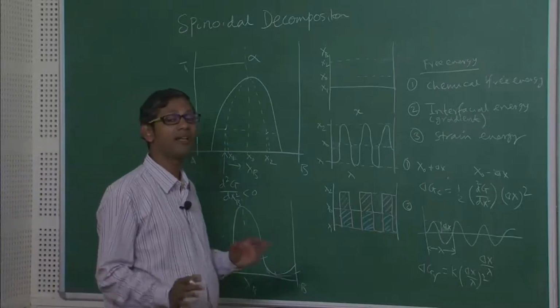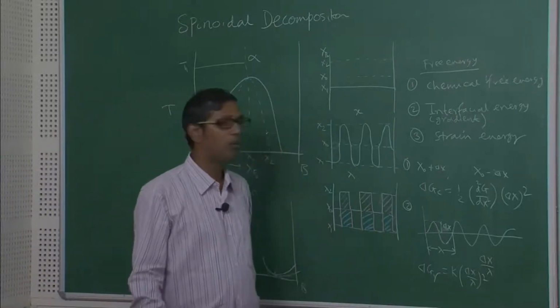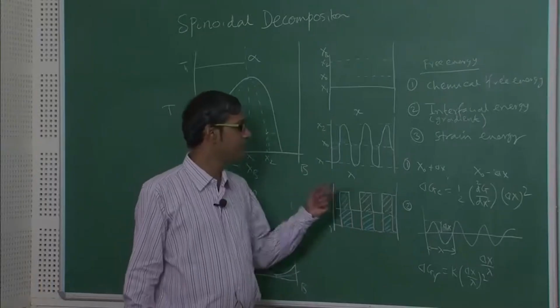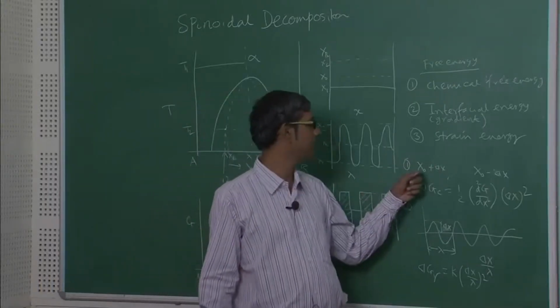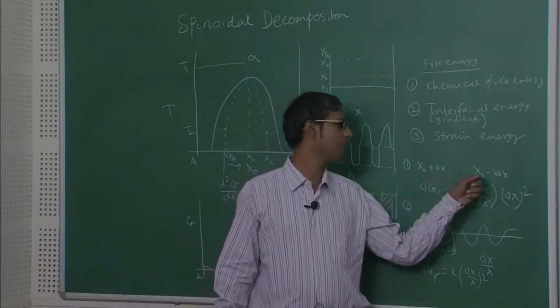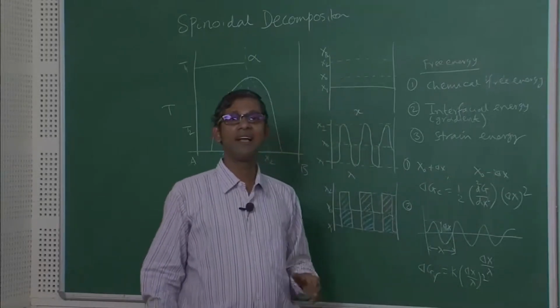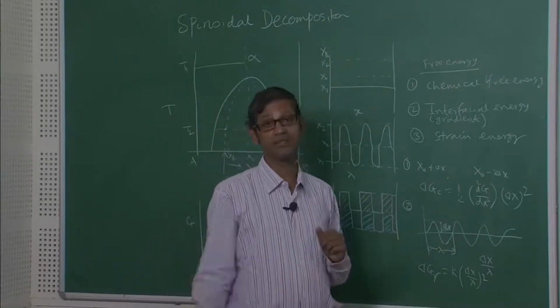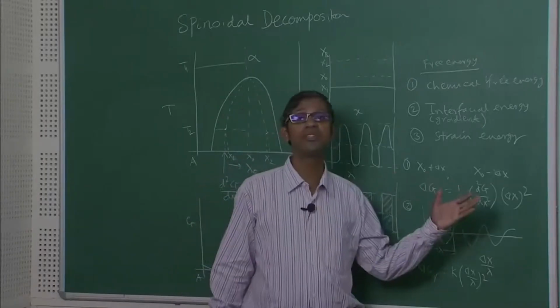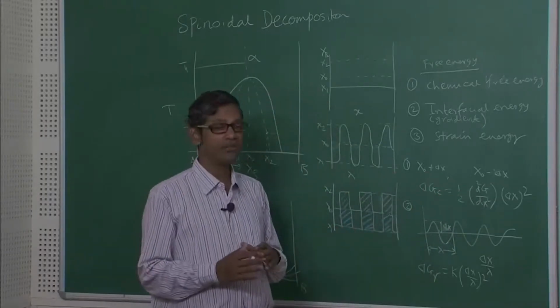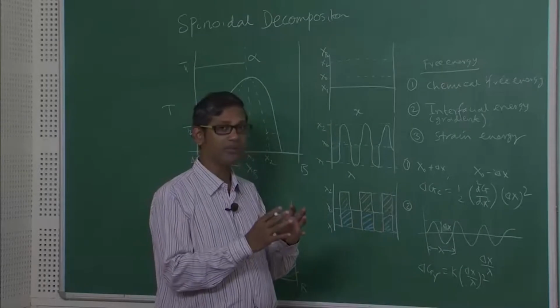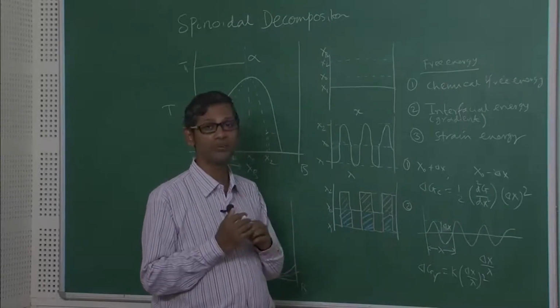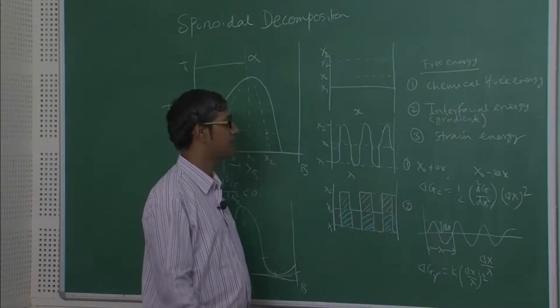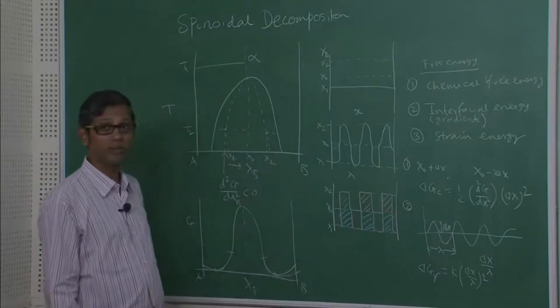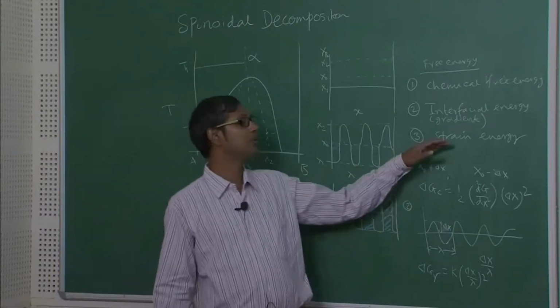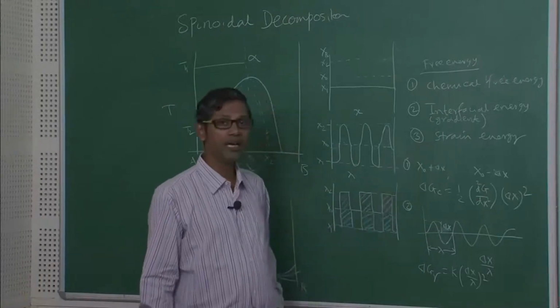Now, let us also calculate the strain energy. First of all, let us understand why the strain energy will at all exist. Well, if the regions which are compositionally different, like a region with composition x0 plus delta x and a region with composition x0 minus delta x, have different lattice parameters, then this will lead to strain energy. Obviously, because if I have a region with a high lattice parameter sitting next to a region with a low lattice parameter, at least elastic strains will be present, and this strain will lead to energetic effects. How do we calculate that?